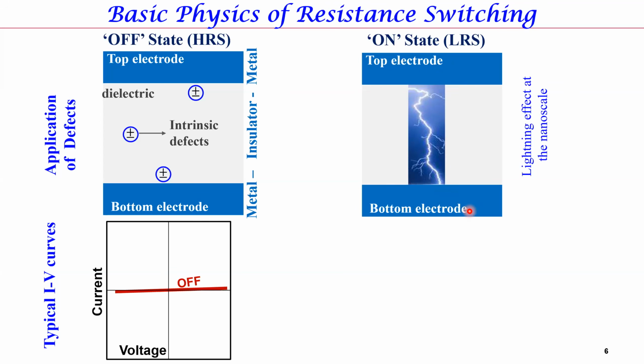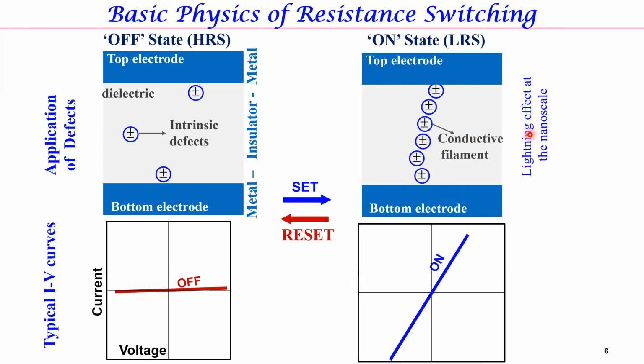So the memory effect, or the switching from the off state to the on state, is very similar to lightning at the nanoscale in solid materials. You apply a high voltage commensurate with the thickness of the dielectric, and if it's sufficiently high, you have a partial breakdown of the material, or ionization of the material. In the case of metal oxides, oxygen debonds from its bonds to the metal, leaving behind oxygen vacancies. These are charge states that can align and form this one-dimensional filament, just like lightning.